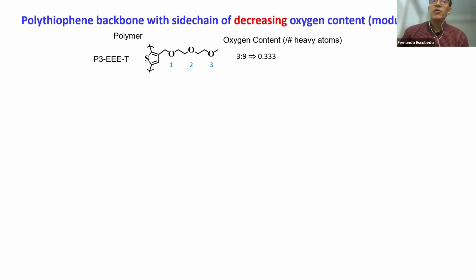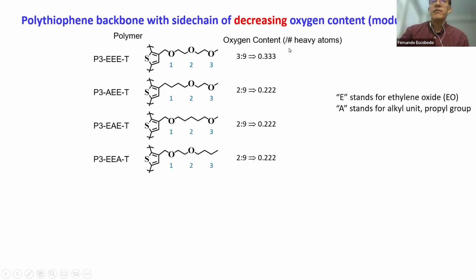So then we explored changing the number of oxygens in this side chain from 3, that gives you a ratio of basically 3 to 9. This is the ratio with respect to the total number of heavy atoms. You can have, for example, variants where you have only 2 oxygens, not 3. And you can put the 2 oxygens in different points along the chain.